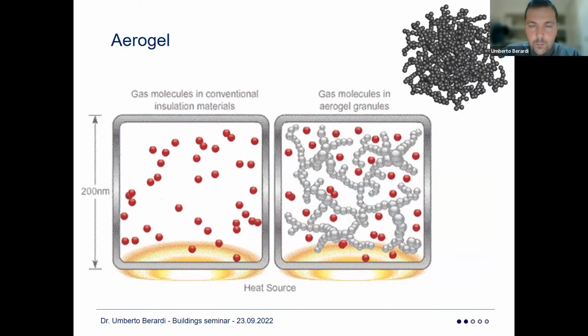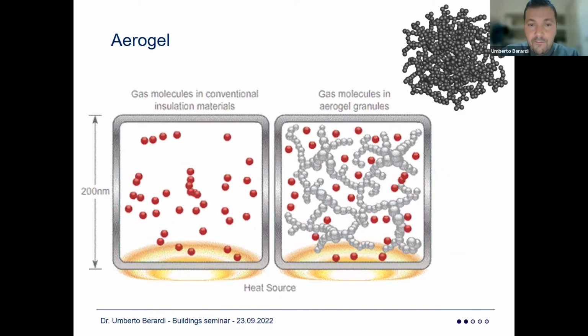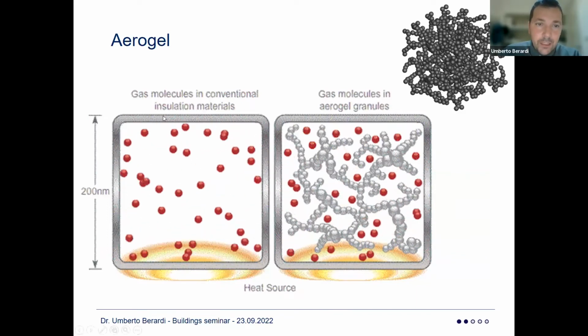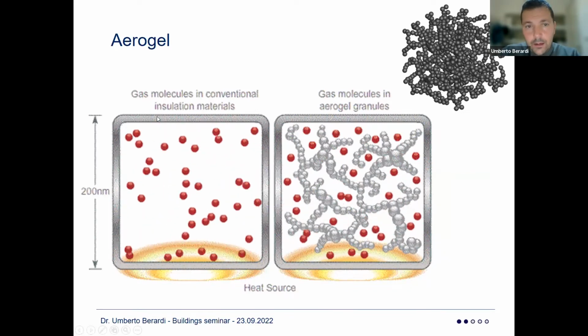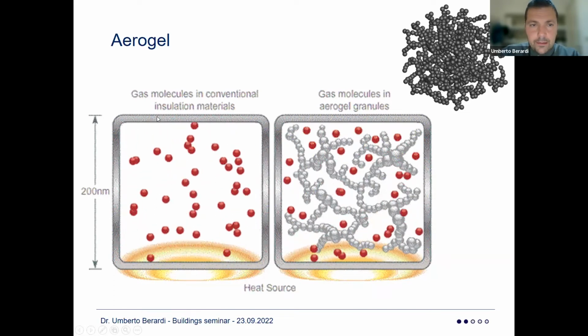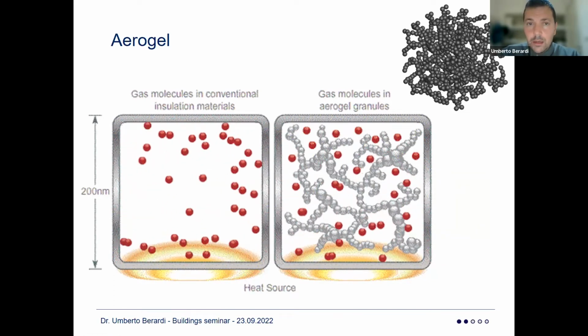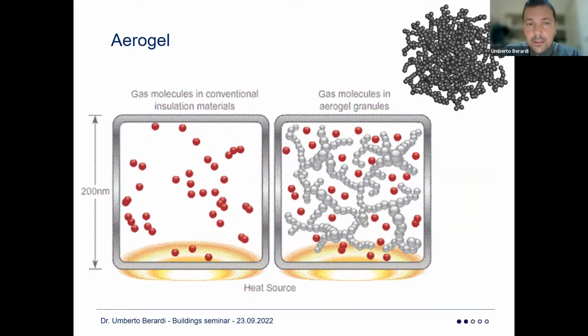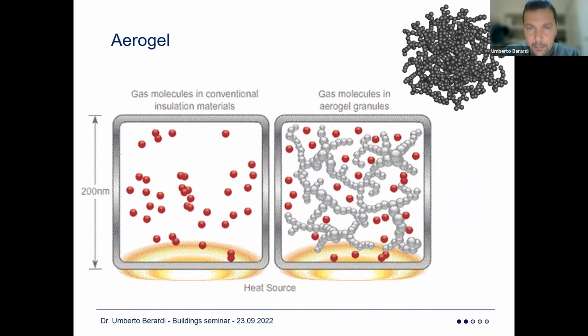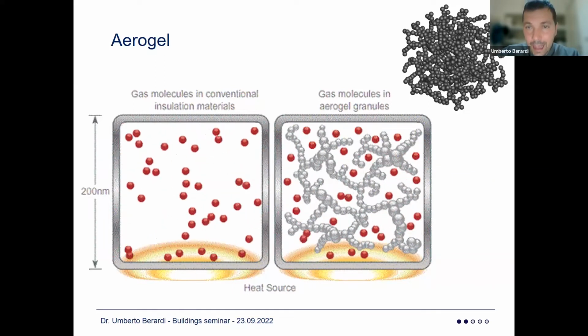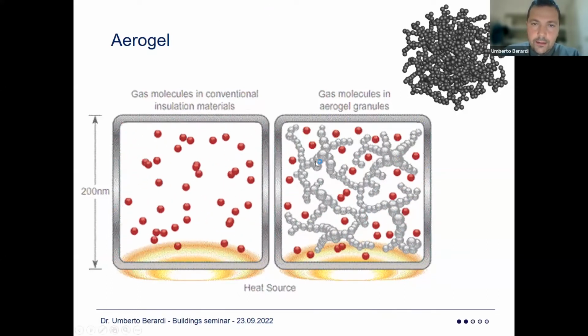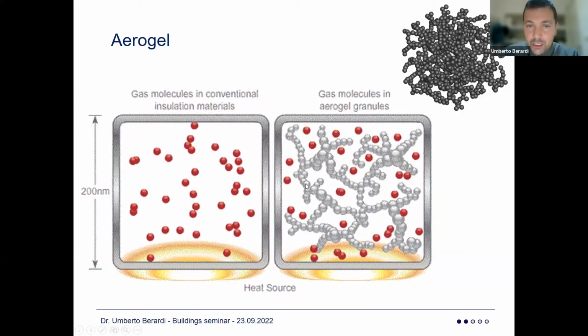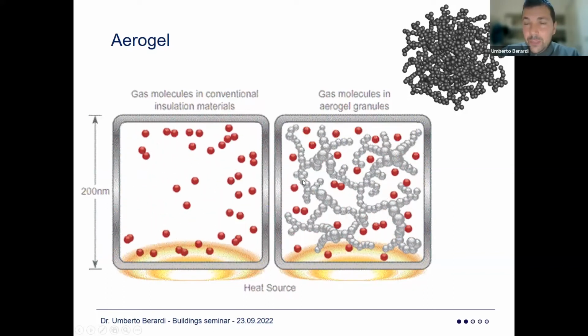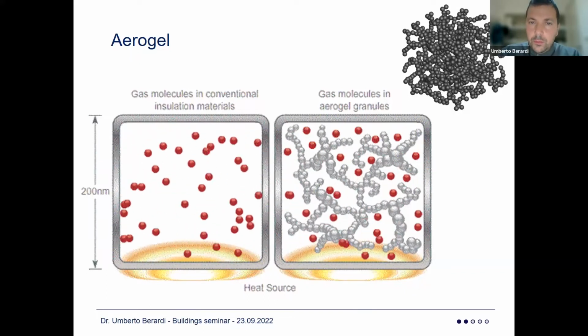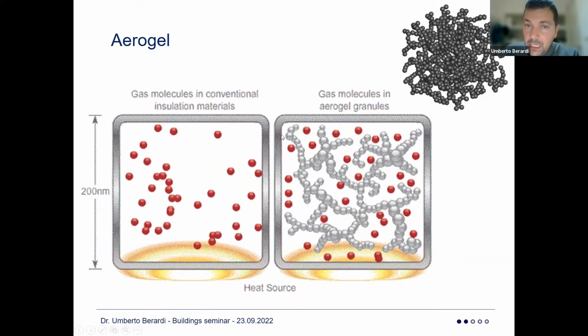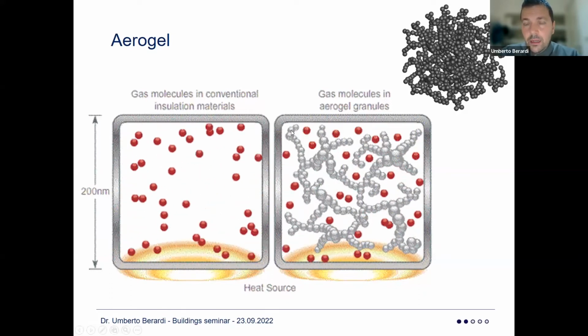Now, where does this product come from? It comes from the idea that if you have a void, as you can see on the left, imagine it is the cavity of a typical mineral wool, particles of air in that structure can move a lot. And that means that they are going to transfer a lot of heat by convection in porous materials such as mineral wool or fiberglass. But if you are capable of structuring a solid material like aerogel in a way that the particles of air don't have the possibility to move a lot and never touch each other, then the heat transfer by convection gets reduced a lot. And if you are also capable of putting an opacifier in the structure of this gray bubble you see here, at the end of the day even the radiation heat transfer gets reduced significantly.